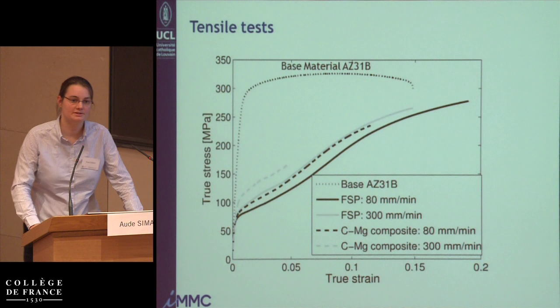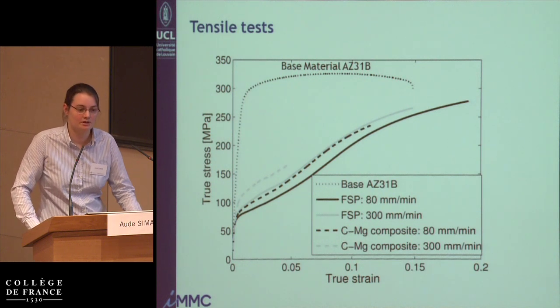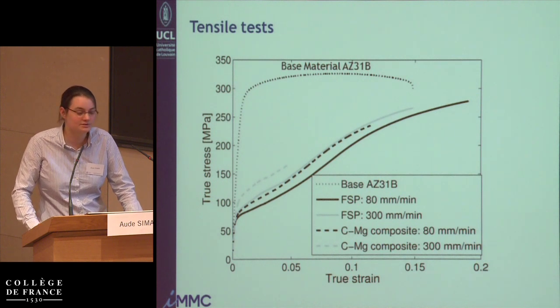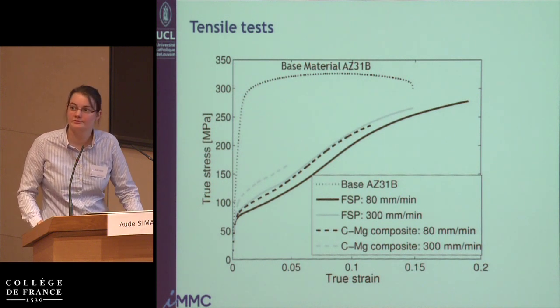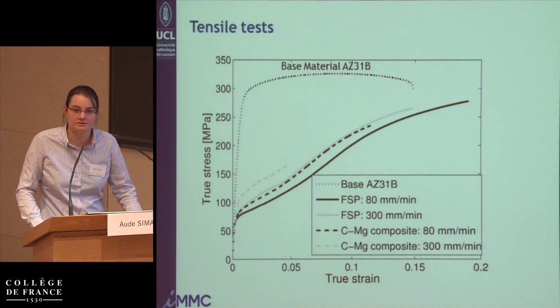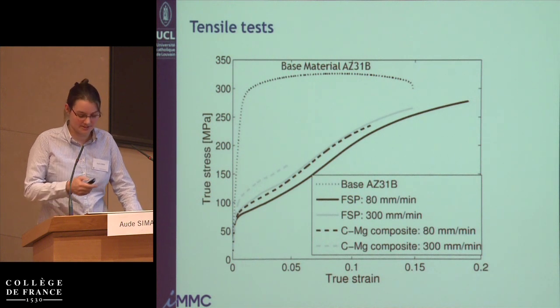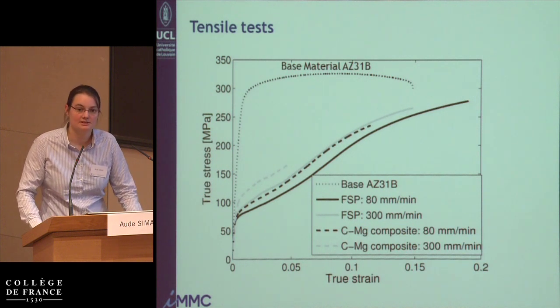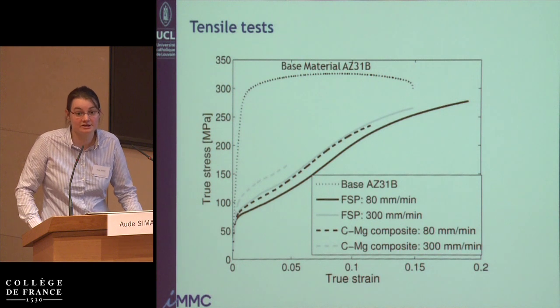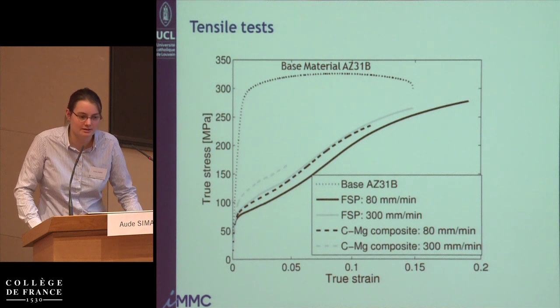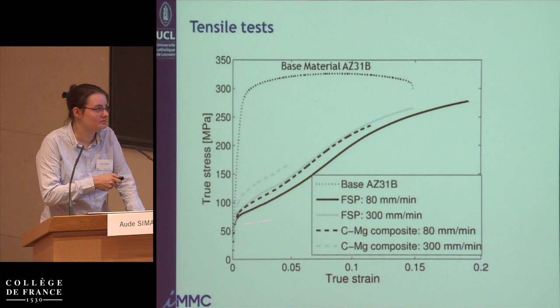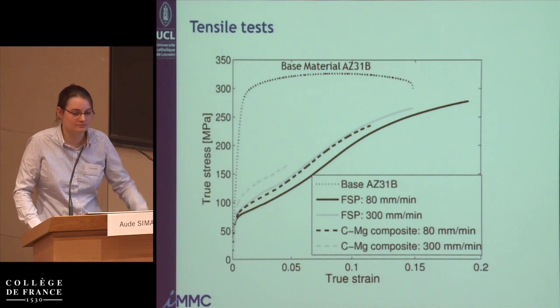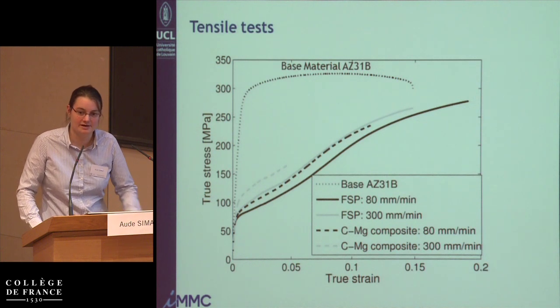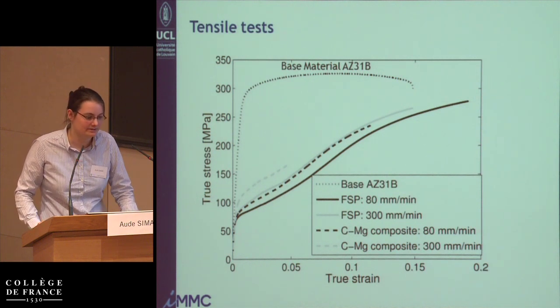So here are the mechanical properties, and again, we are talking about low volume fraction of carbon fibers. So the improvement of the material is not sufficient yet to really have a serious improvement in the material. And also the base material is much larger, and that's because that material was strain hardened. It was a rolled material, and we are recrystallizing it. So basically we should start from a recrystallized material to compare with a recrystallized material that would be much lower here. But here we started with this AZ31 material that was rolled for having sheets, and so we are comparing things that are really not comparable.